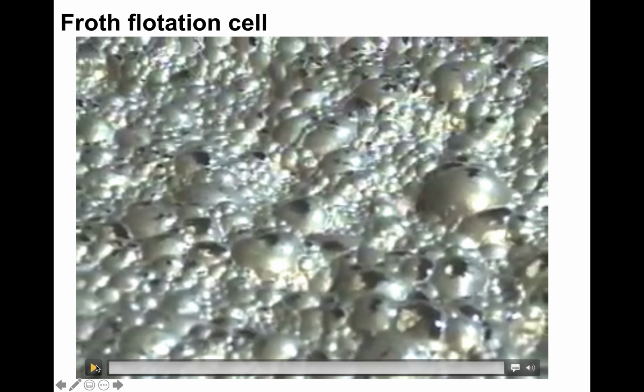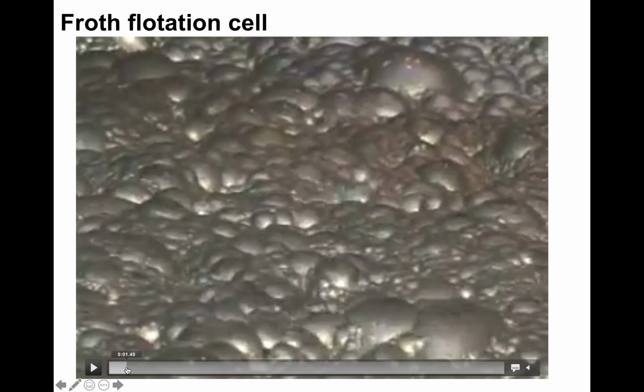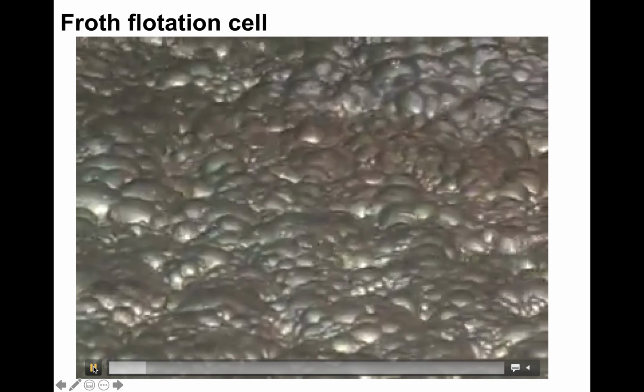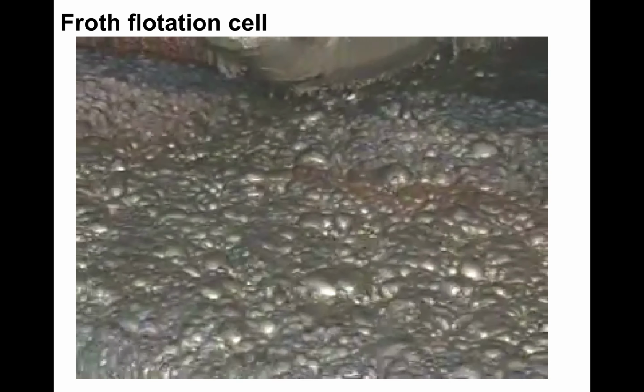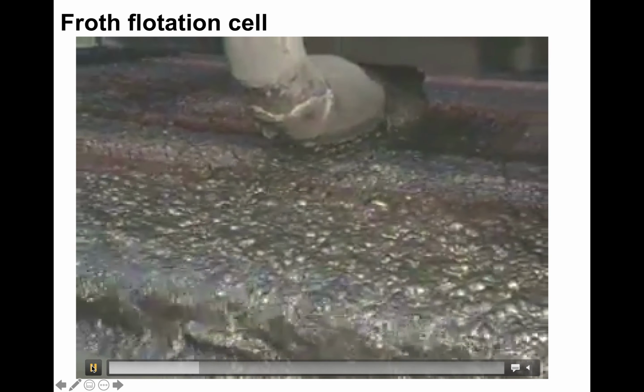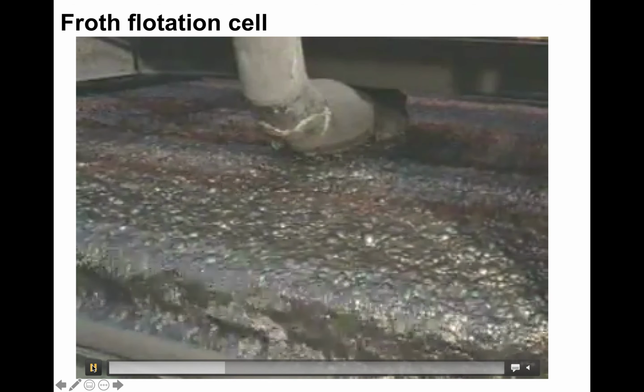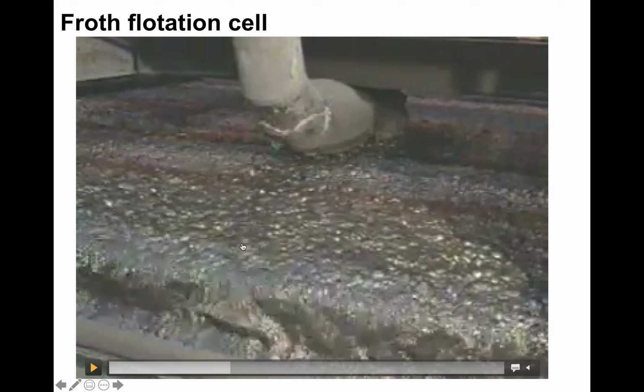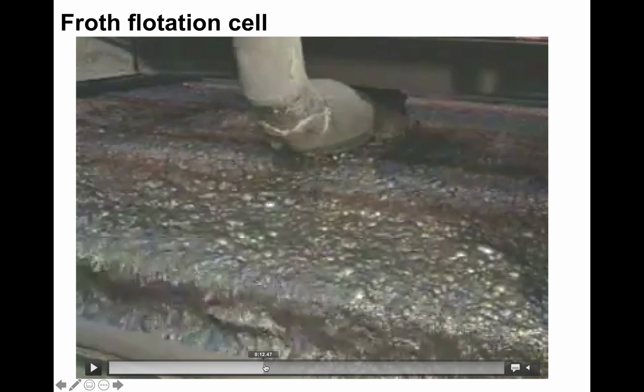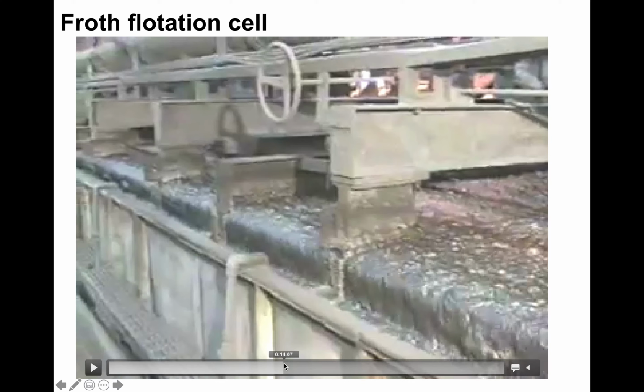So this is what you would see at the top of the flotation cell. Here you're looking at bubbles that have risen to the surface of the flotation cell, and the color is literally the color of the chalcopyrite sulfide minerals. And notice here on the sides that all of those bubbles and the chalcopyrite that coats the oil on the bubbles is being scooped off the side into a trough. And when it's scooped off the side into a trough, it can be collected.